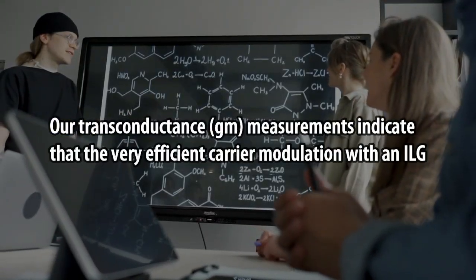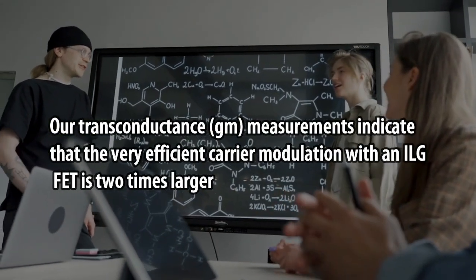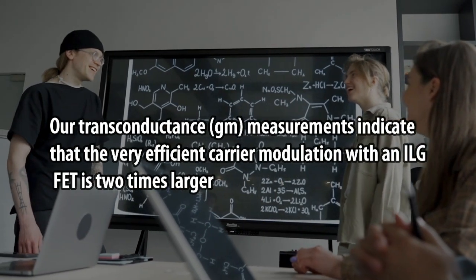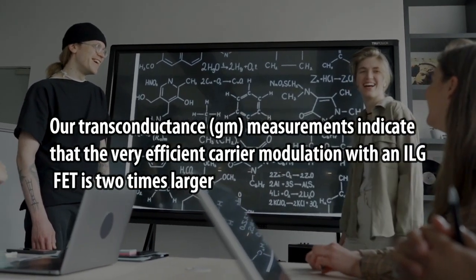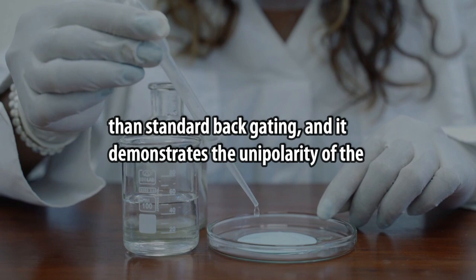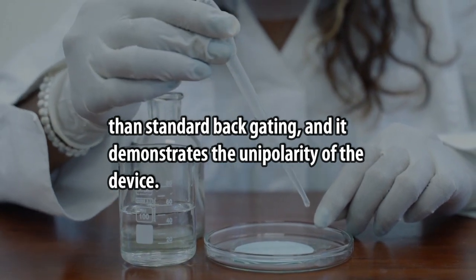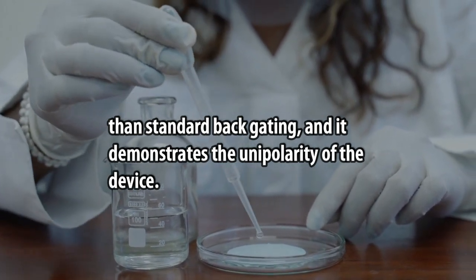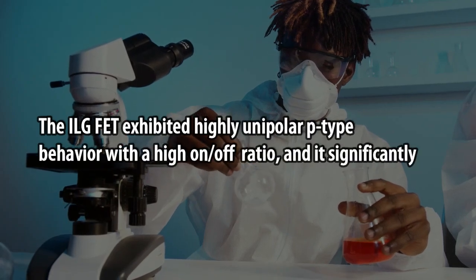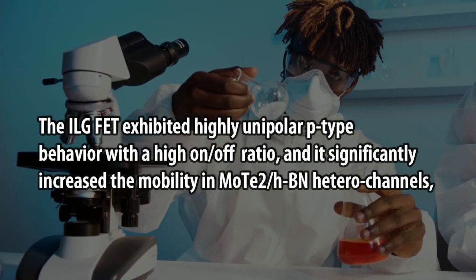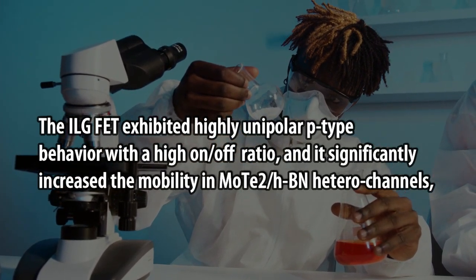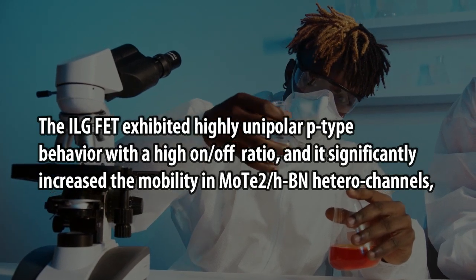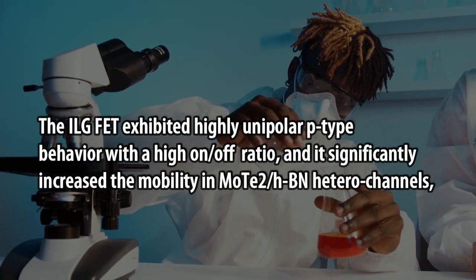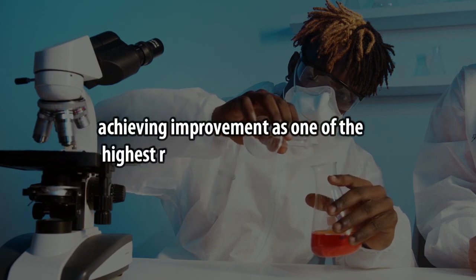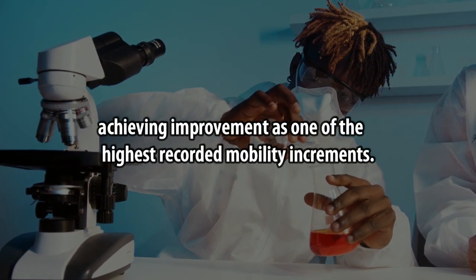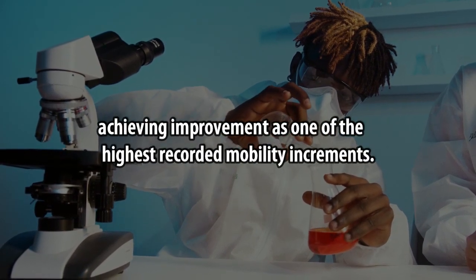Our transconductance (gm) measurements indicate that the carrier modulation with an ILG FET is very efficient, two times larger than standard backgating, and it demonstrates the unipolarity of the device. The ILG FET exhibited highly unipolar p-type behavior with a high on-off ratio, and it significantly increased the mobility in MoTe2 hBN heterochannels, achieving one of the highest recorded mobility increments.